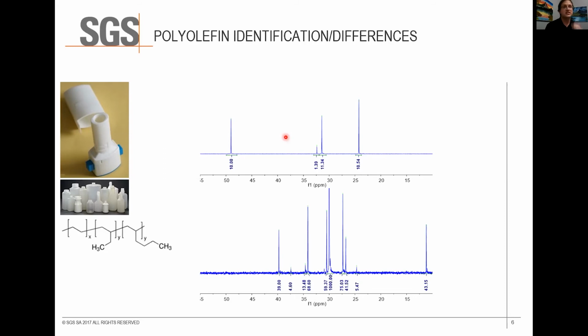The top spectrum here is a blend of polypropylene with a little bit of polyethylene blended in. It's not a copolymer, because if it were, you would see a few additional signals in the 45 to 35 range, and between 20 and 30, where you have an individual ethylene unit surrounded by polypropylene. That causes enough of a sequence break that you see a couple signals there that let you quantify them. The symmetry of that makes backing that out into the weight ratio of monomers a little tricky - you have to consider that sometimes identical groups came from different initial monomers.